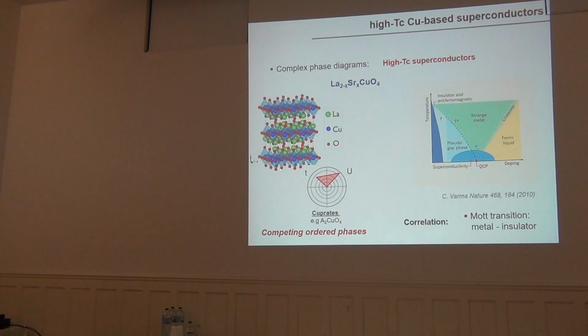What I'm doing here is that my parent compound, which is basically these copper oxide planes, separated in this case by lanthanum, is doped with strontium. The parent compound, this lanthanum strontium cuprate, is an antiferromagnet. So I'm here in this antiferromagnetic phase, but by doping the system, you are charging, you are introducing holes into these copper oxide planes, and basically you go into this superconducting phase with